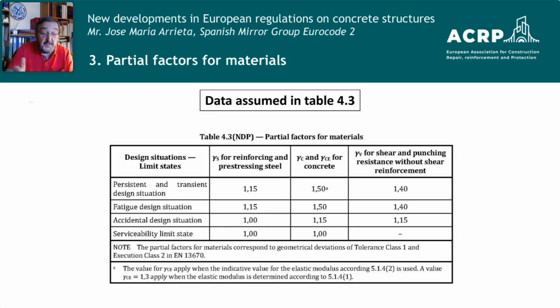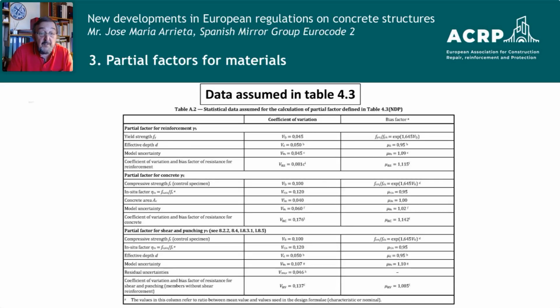We see that these coefficients correspond to deviation of tolerance class 1 and execution class 2 in EN 13670, the execution of concrete structures code, and also that they correspond to some statistical data of the variables, with the coefficient of variation and the bias factor. So, for example, for yield strength, we have the coefficient of variation, also for the depth, also for the model uncertainty. And with these values, we obtain the coefficients of table 4.3.